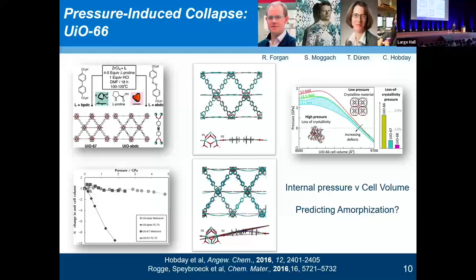And so that means when we're looking at a snapshot of where those linkers are, they're actually bowing out of the plane. You might think, oh, well, that's really good. But I mean, come on, Tom. I mean, it's 9:15. We've got up, and you're telling us, well, that's great structural work. But what does it mean? Well, actually, when you compress these, UiO-67 dies, right? We love killing MOFs in my group. UiO-67 dies very quickly, but the functionalized version does not. And that's really because this linker bowing is enabling the structure to accommodate more strain before collapse. So if we're designing pressure resistant MOFs, flexibility is a very good thing indeed.